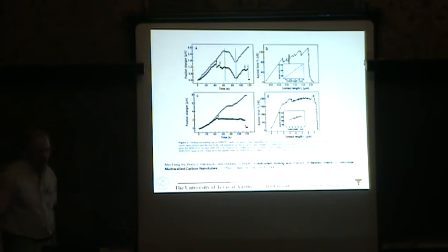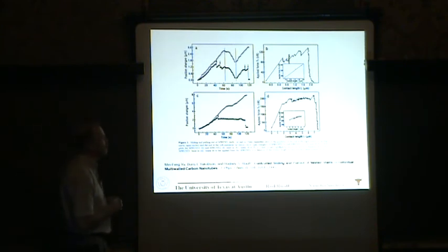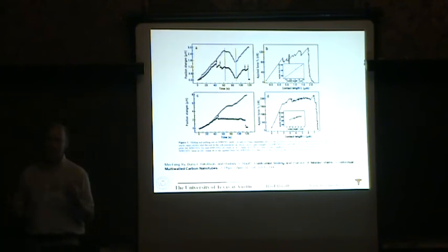And so as we plot the position changes of the cantilever tip versus time, we video recorded the experiments, we end up with stick-slip behavior that can be mapped in terms of a shear strength and a contribution in terms of this edge effect. And so we ended up with two different responses in a sense.